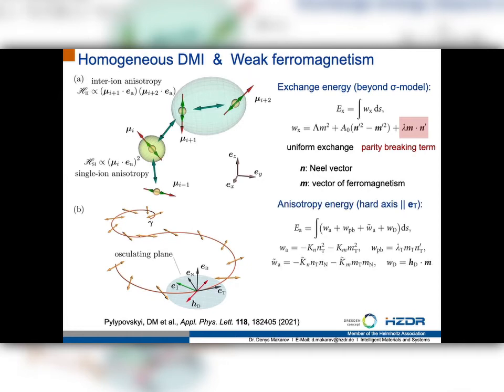And this is exactly something which I would like to discuss very briefly here. You can write also for the same model that we discussed before, a one-dimensional antiferromagnetic spin chain with a dipole-dipole interaction, where you have hard axis anisotropy parallel to the tangential direction. In this case, you will be able to get also terms which are proportional to this omega D type of term, where you have a homogeneous DMI hidden there. This H_D is a Dzyaloshinskii field which is related to the homogeneous Dzyaloshinskii-Moriya interaction.